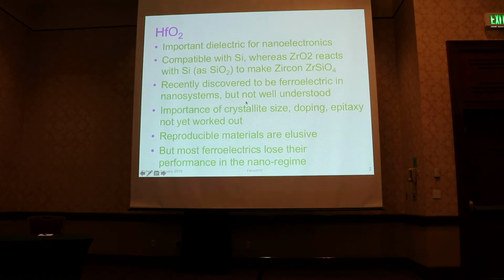Okay, there we go. So Hafnia is a very important material that's in nanoelectronics. It's used as a gate material in the dielectric, and it's compatible with silicon. So is zirconia, except zirconia reacts with silicon to make zircon, so it's not really ideal, whereas Hafnia tends not to. And recently, by recently I mean in the last decade, it's been discovered to be ferroelectric, which was rather surprising. It's not ferroelectric in bulk, it's ferroelectric in nanosystems, but it's not very well understood. And the properties are very dependent on crystallite size, doping, epitaxy, and really it's not worked out experimentally or theoretically yet. So it's really quite an interesting area.